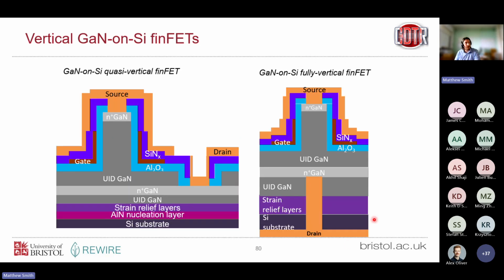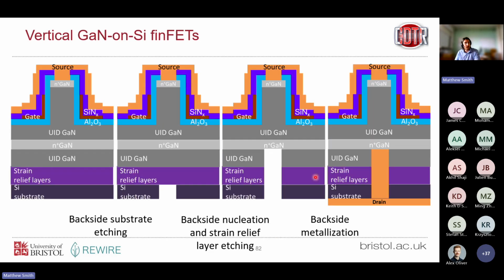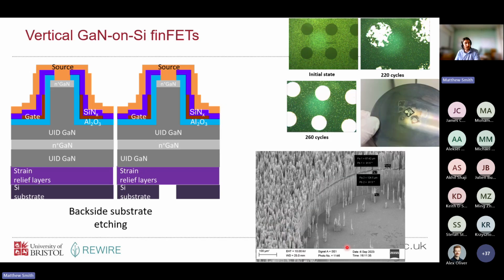And again, our next step is to make these fully vertical devices. So similar to what others have done, etch through this silicon substrate, etch through our strain relief layers, and then stop on our embedded GaN layer here. This is very non-trivial. So this is several hundreds of microns thick. This is several microns thick. This is a few hundred nanometers. So stopping on this 200 nanometer thick layer is going to be quite challenging. We have made some progress there, so we're able to etch through the silicon and stop on the GaN quite nicely. But yeah, this is ongoing work, so watch this space.